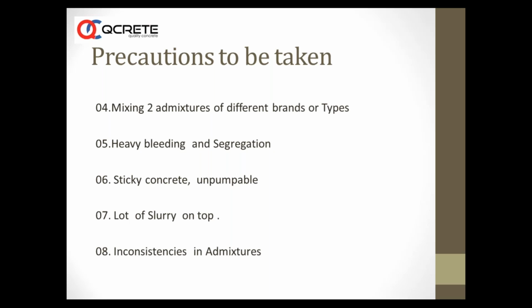If we have a high slump concrete or SCC or SDC concrete, and by chance somebody vibrates it too much, or it's a free flow concrete and you allow a customer to vibrate it excessively, then slurry comes on top. So it is not to be blamed on the admixture - it is not a problem of the admixture, it is a problem of handling on site.